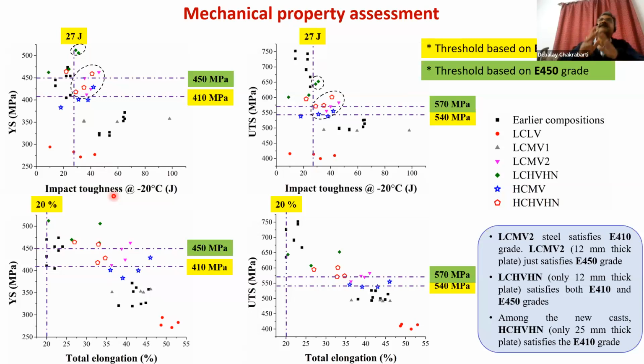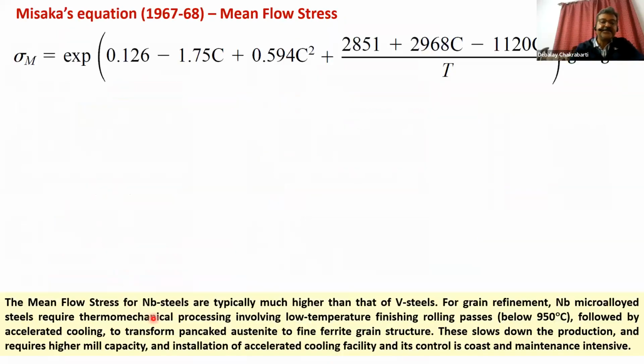So overall, this is what I want to show. And as I said, one of the biggest advantages of this vanadium steel is that rolling load remains low. So the steel becomes rollable. Cracking problems do not appear since we do not need low temperature deformation.